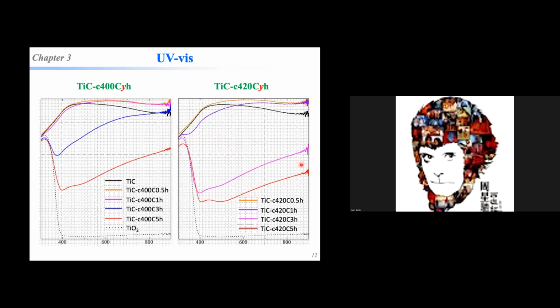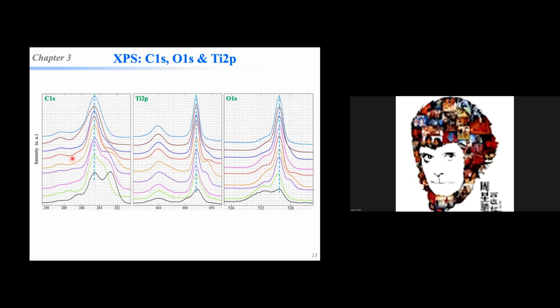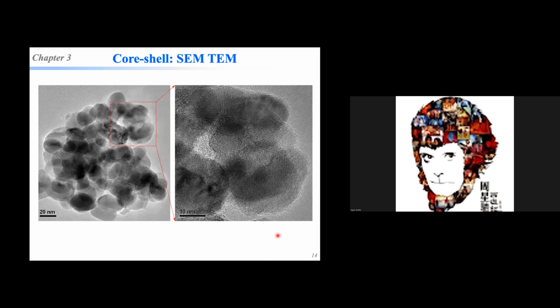And the XPS result also shows something like this: the TiC peaks disappear, and this also shows the TiC peaks changing. This shows the TiC response, and the oxygen vacancy may become decreasing with increasing temperature. This is because of the oxidation of the TiC.